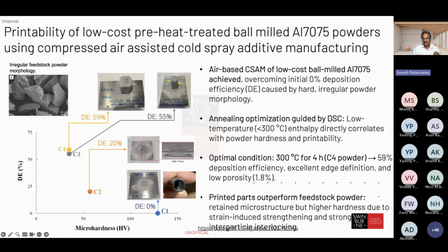So the deposition efficiency will determine how far. If you're putting in 1 kilogram of powder, and you're getting 800 grams of a part and 200 grams might go off, that's really good deposition efficiency. But if you're achieving anything less than 50%, that's not really good. So what we did, with the low cost powder feedstock, we achieved significantly higher than other people who have done work in this area, close to 60% deposition efficiency, which is really good for a low cost aluminum 7075 powder, the 7000 series powder.